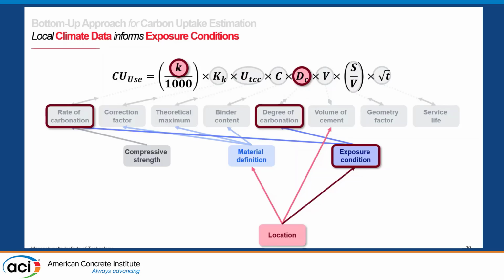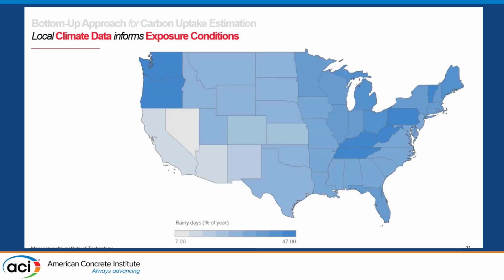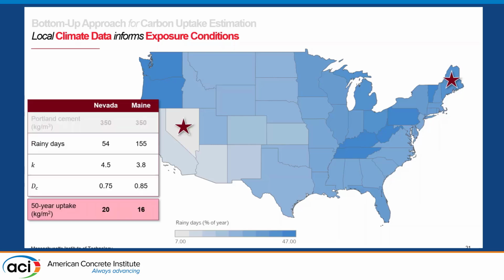Local data also includes information about the climate, which affects the exposure conditions, specifically for surfaces that are outdoors, because climate includes a breakdown of rainy to non-rainy days. Again, this map shows a gradation of the percent of rainy days in a given year, where the lighter blue colors are the drier states on average, and the darker blue are the rainier states. And going back to the same example, even if we assume the same amount of Portland cement for both of these locations, Nevada and Maine, Nevada is relatively drier in climate, and Maine is relatively rainier.